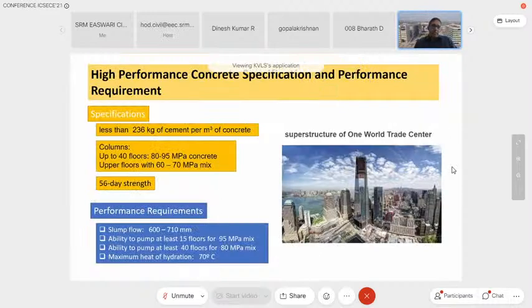Now, there are other such examples that are now coming forward. And I want to take the example of the superstructure of the One World Trade Center. The kind of specifications that were put in place for concrete that went into this One World Trade Center was that less than 236 kgs of cement could be used per cubic meter of concrete. Now, this is a very severe requirement. Most of us know that 236 kgs of cement per cubic meter of concrete would basically probably hurt strength. But they did not compromise on the strength either. They said in columns up to 40 floors, concrete had to achieve 80 to 95 megapascal strength, and in the upper floors the concrete had to achieve 60 to 70 megapascal.